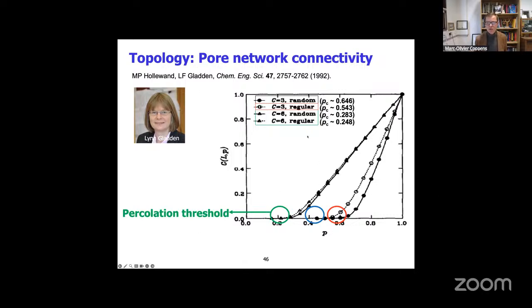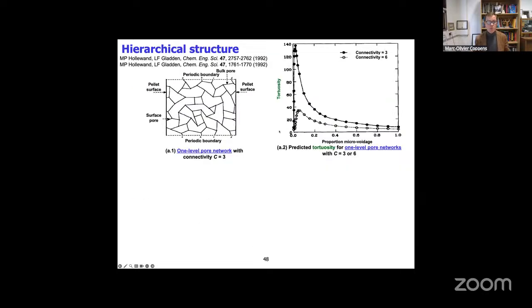And an image like this can already show you what that means, how connected it is, right? And what she also showed with a former student, Michael Hollewand, is that if you just take a classical model where you have connected pore spaces, and you assume that some of these links are connecting and some are not, when you have a very low fraction of micro void, as she calls it here, then you get these extremely high tortuosities. You can get factors of 100 or so, especially when the connectivity is low.